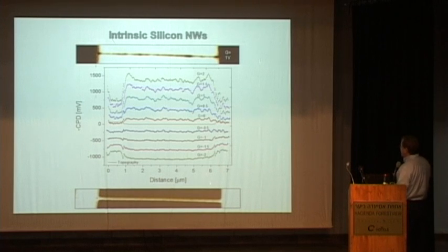These are negative applied bottom gate voltages, and these are positively applied gate voltages. And you can see that for a negative gate voltage, we don't see any structure in the wires. But when we start applying from, let's say, minus 0.5 volts and going more in a positive direction, we're starting to see bumps in the nanowires.